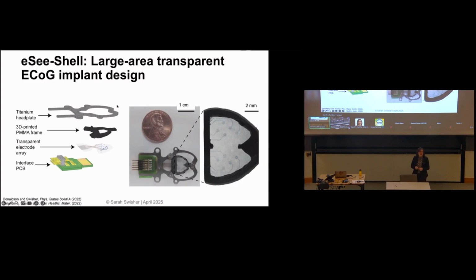And then we said, well, what if we actually put electronics on that and we make it a sensor as well? So we used a transparent conductive material. It's called PEDOT. It's a polymer that conducts electricity well. And we deposited these electrodes, and you can see them by eye, but the way that we do the imaging through this, about 70 to 80% transparency, which is what these are, is sufficient so that you don't lose the optical signal to noise.